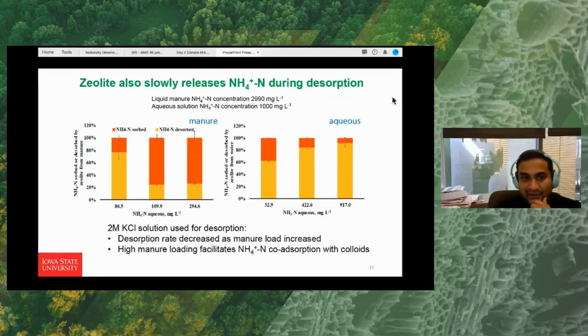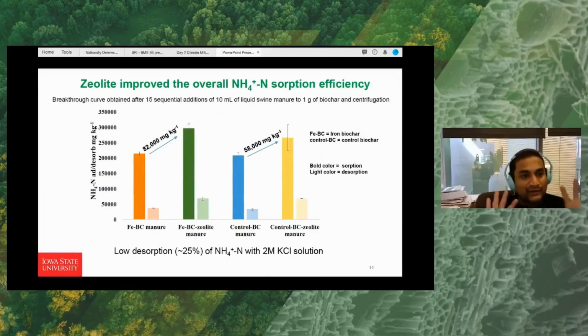Next slide, please. So if we compare the overall system of the biochar and zeolite, we have shown that zeolite overall improved the ammonium absorption efficiency. So we did the breakthrough curve after 15 sequential additions of 10 milliliters of liquid manure, with 1 gram biochar and centrifugation. For the iron biochar system, zeolite increased the absorption to around 82 milligram per gram, or 82,000 milligram per kilogram. For the control biochar system, zeolite improved ammonium absorption by around 58 milligram per gram, or 58,000 milligram per kilogram, compared to the biochar system alone.